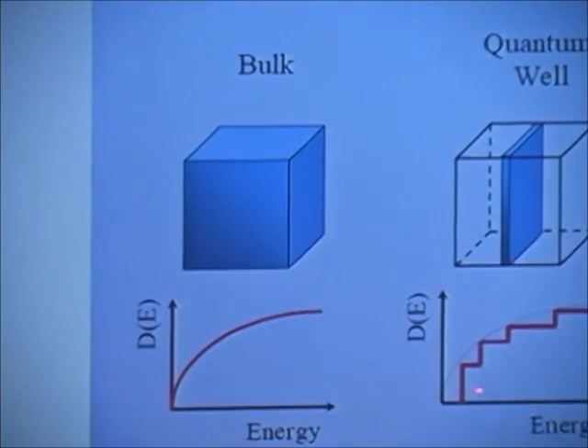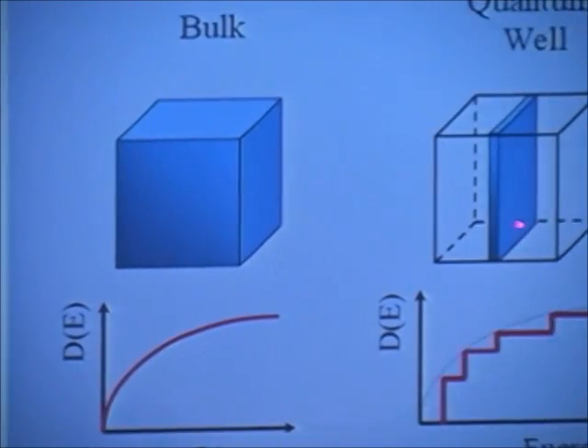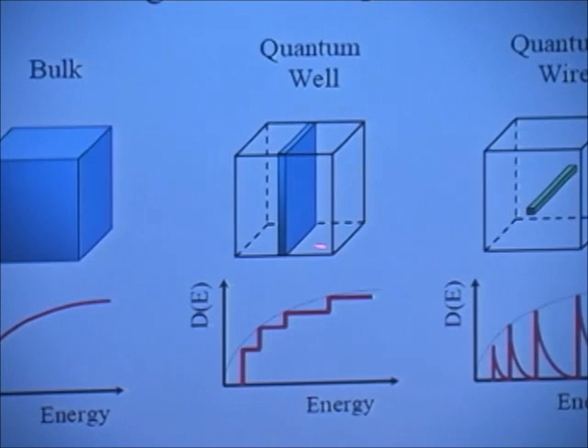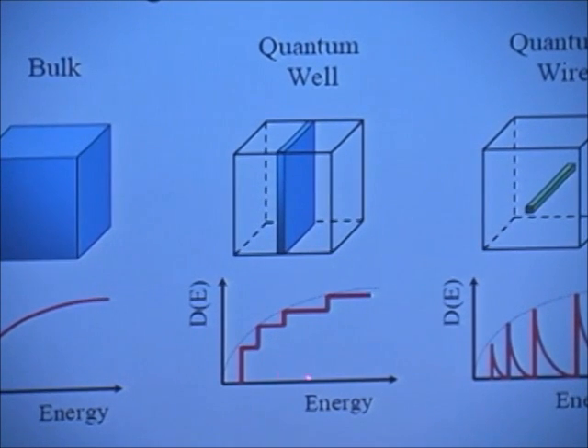And here we see what happens if we have a quantum well. In 2 dimensions, we have a constant density of states. But every time we add a new state to this, it jumps up. So it forms this sort of pattern. Essentially, a 2-dimensional electron gas or 2-dimensional system has a constant density of states. But every time we add a new level, then we add another. So we get a step function like that. And in fact, it approximates the 3-dimensional case. You can see the envelope there being the same as 3 dimensions like that.